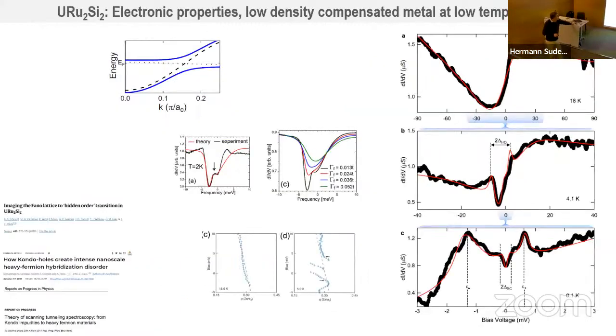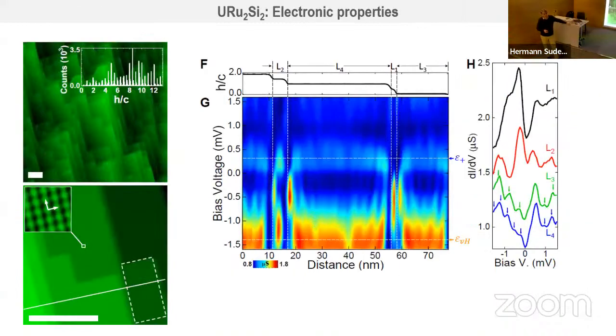This was possibly the closest result obtained before our work. So we do our STM experiments, where we have reproduced what other people have been measuring. I'm not going to present details, but essentially this is a Fano anomaly. This is the gap related to this kind of strange order. And here you have the superconducting gap. So it works. And now let us go on to what happens on the surface.